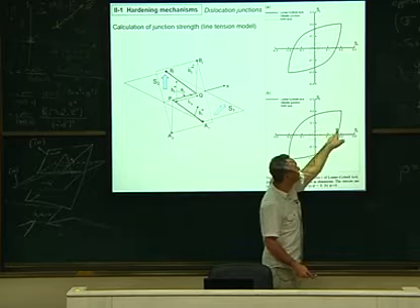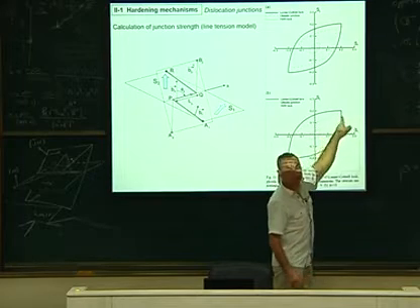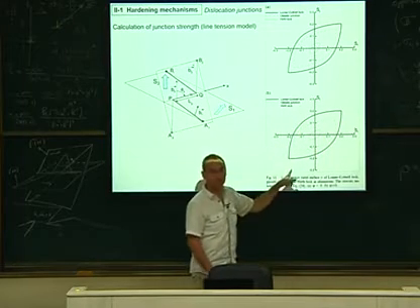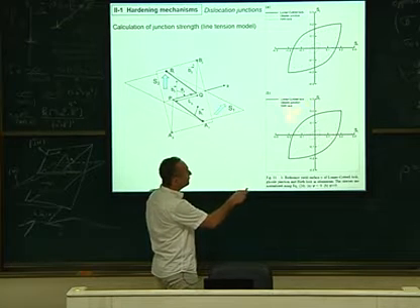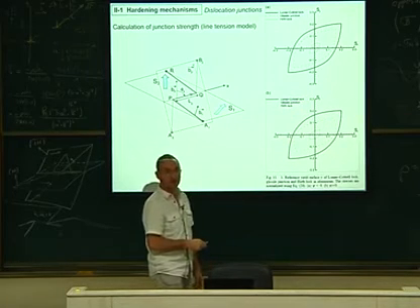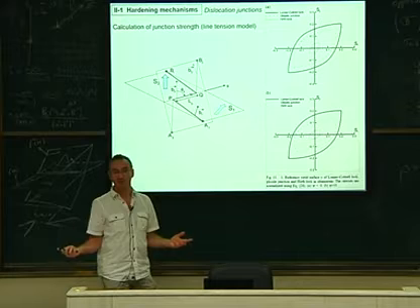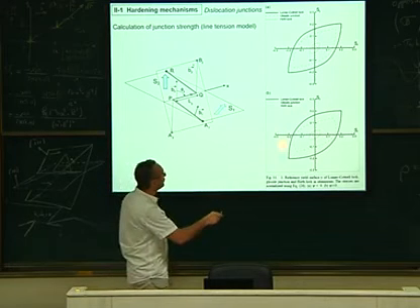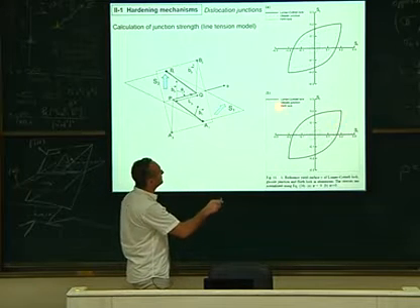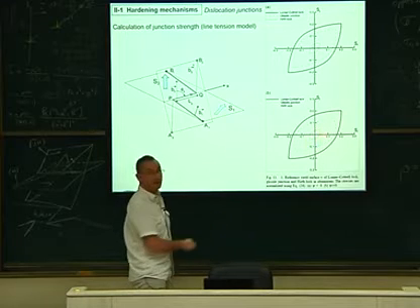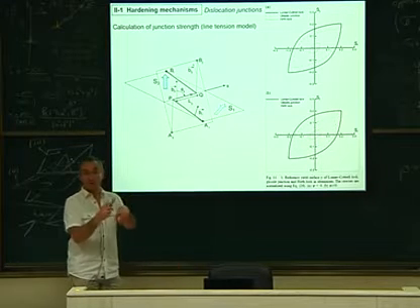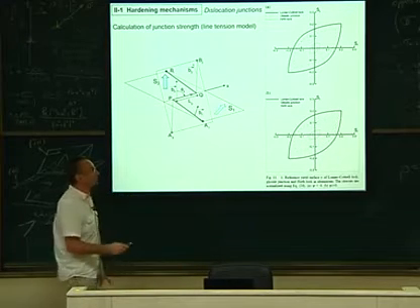I can do that with such a path, such a path, such a path, and then I can plot what I call the yield curve for a given junction. Here I did it for Lomer-Cottrell, glissile, and Hirth, and you have all the curves here, and you can visualize which is stronger than which. You can see that the Lomer-Cottrell is very strong, the glissile is here, and the Hirth is there, very weak, just because of the local energy. The Hirth is the weakest one.